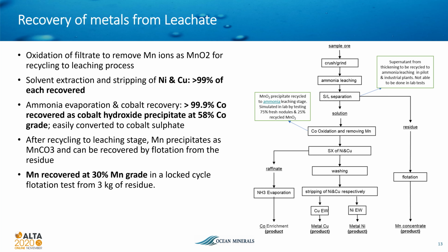Now look at the centre part of the flow sheet. Following removal of the manganese from the leachate, nickel and copper are recovered by solvent extraction processes. In this test work, copper and nickel metals were then recovered by electrowinning from the solvent extraction solution. However, after solvent extraction, instead of producing metals, other processes may be followed to produce copper and nickel salts, depending on end markets such as electric vehicles. Cobalt is recovered following ammonia evaporation as shown on the flow sheet. Excellent product grades and overall metal recoveries were achieved with this process.